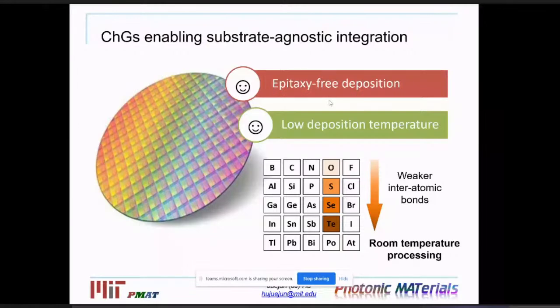Now, more importantly, these materials can also be deposited while keeping the substrates at room temperature all the time. This again has to do with the unique bonding nature in these chalcogenide glasses. Compared to oxides, like I mentioned, chalcogenides have weaker interatomic bonds. As a result, when you're doing vapor phase deposition, it takes much less energy to break these chemical bonds, so the thermal loading on the substrates is significantly reduced. This attribute means that we can process these materials at room temperature. This is important for applications such as integration on polymer substrates, where you don't want to cook the substrates.